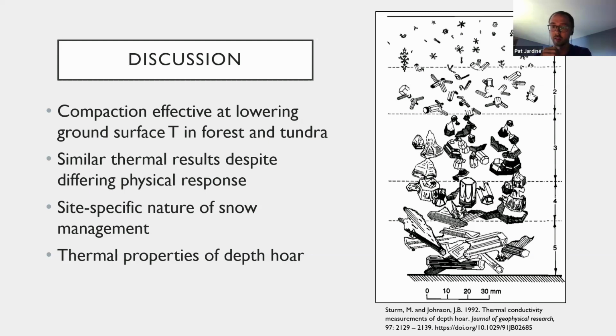And this was even in snow with density in the range of 200 to 300 kilograms per cubic meter, so it's highly unusual. The snow was described as being held together so loosely that it broke apart at the slightest touch, and that's what was observed right at the bottom of the snow at the Dempster field sites. In Mayo, the depth hoar layer was clearly visually distinct from other layers, but its hardness and density were nearly the same, and that makes me suspect the depth hoar was at an earlier stage of metamorphism.